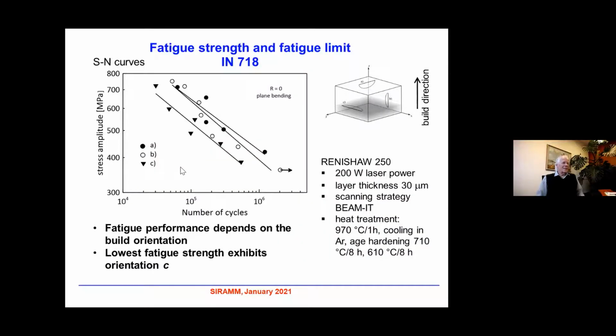Now, I would like to show you results on a completely different material, namely Inconel 718. This material was manufactured on another machine named Renishaw 250. The laser power was nearly 200 watts, and the layer thickness was 30 microns. Again, the scanning strategy was a multi-directional strategy. The heat treatment in this case was the following: 970 centigrades for 1 hour, then cooling in argon, then age hardening at 710 centigrades for 8 hours, and then 610 centigrades for 8 hours. It means quite complicated heat treatment.